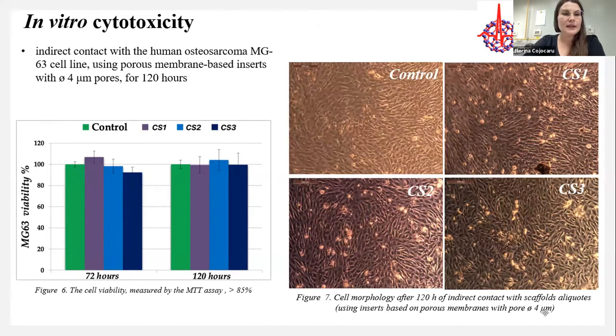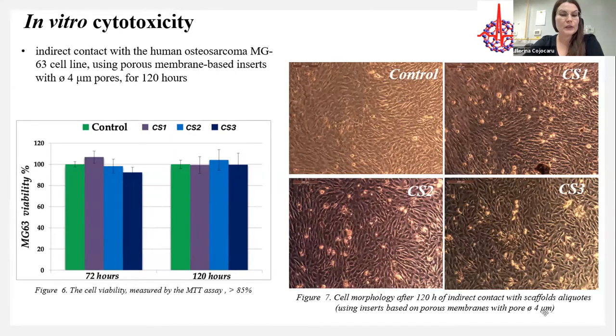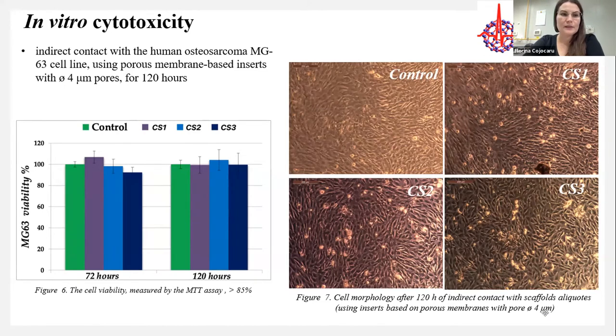In vitro cytotoxicity was studied in indirect contact with a human osteosarcoma MG63 cell line using porous membrane-based inserts. Cell viability measured by MTT assay was proved to be higher than 85%, meaning the scaffolds are non-cytotoxic. Moreover, we studied cell morphology after 120 hours of indirect contact with scaffolds, and it can be seen that the form of the cells and their spreading is similar in control and in wells containing scaffold aliquots.